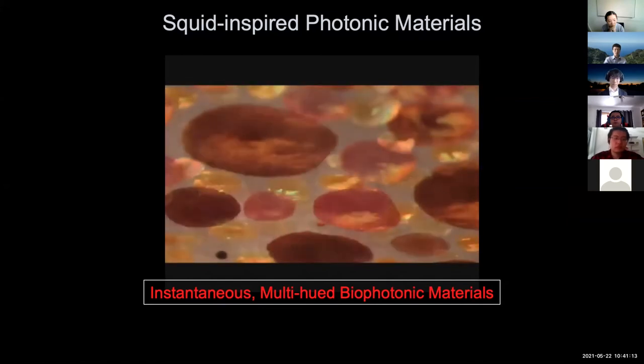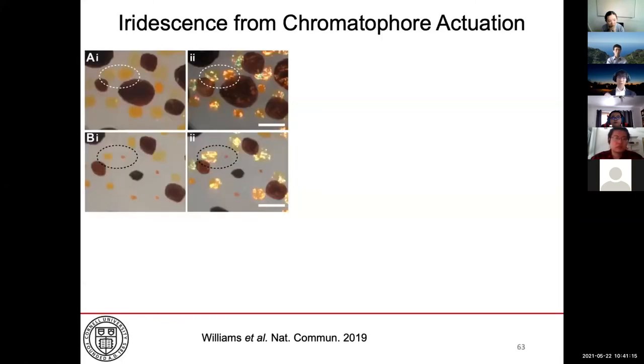Now, by shining a light on the chromatophores as they actuate, my experimental collaborators found that it does not just present chromatic coloration, it also iridesces simultaneously. And this observation actually runs against the grain, because usually iridescence originates in iridophores. They are located in a separate region, such as beneath the pigment cell. And therefore, for us to fully unravel the structure and function of the squid chromatophore, we start going down the